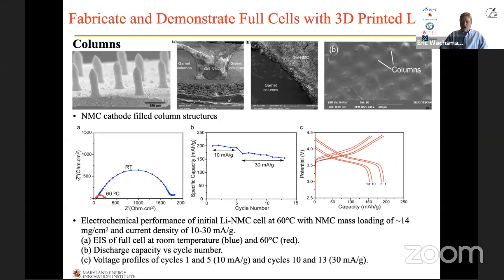And as you go to higher current densities, which would be, for instance, the 30 milliamps per gram versus 10 milliamps per gram, you get less capacity. This is very typical for batteries. So you have a trade-off in energy versus power. At high cycle rates, you get more power, but you don't get as much energy because you're cycling at a faster rate. Okay.